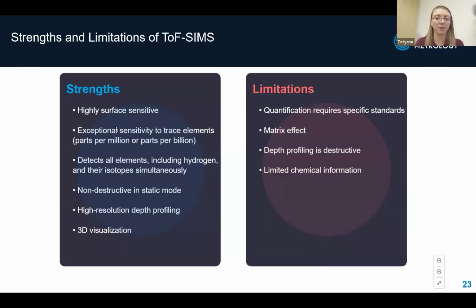However, it is important to remember the limitations. Quantification isn't straightforward. It requires specific standards. Matrix effects can complicate the interpretation. Depth profiling is destructive to the sample. And while ToF-SIMS excels at elemental analysis, it provides limited chemical bonding information compared to techniques like XPS, for example. Understanding these strengths and limitations is key to using ToF-SIMS effectively.